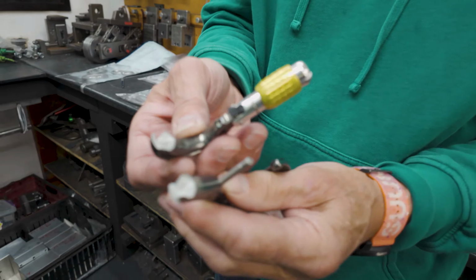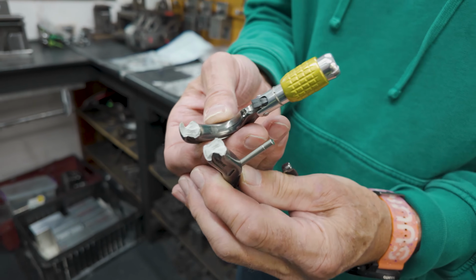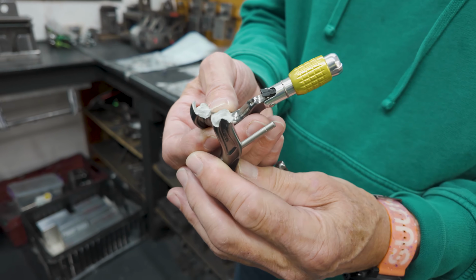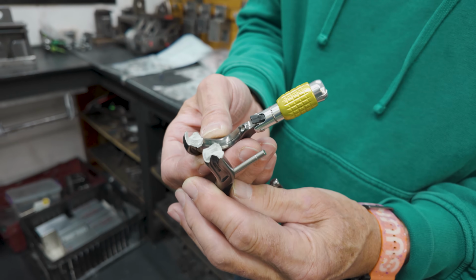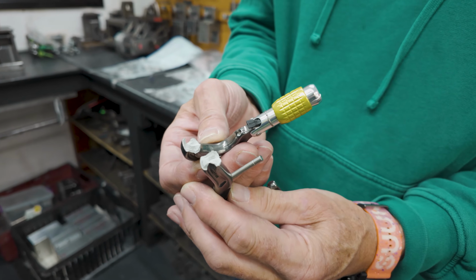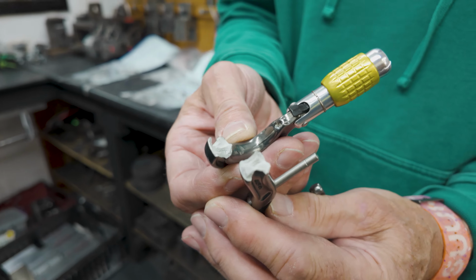And we've actually broken the back at 29.1 kilonewtons. So here's the broken parts of the carabiner, and as you can see, if we inspect it, we're looking for a very nice fine grain structure, which would be indicative of the heat treatment having been carried out correctly.